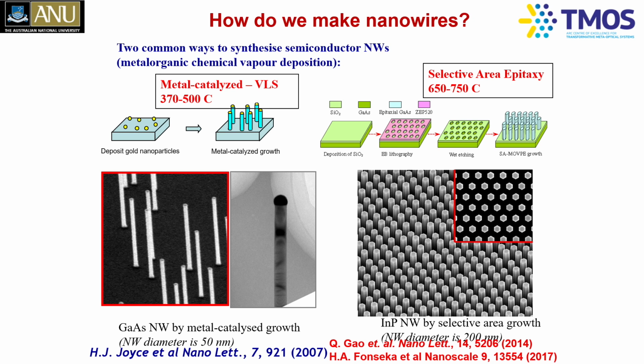Put this into the MOCVD reactor, heat up to somewhere between 650 to 750 degrees Celsius, and introduce the gases needed for the growth of indium phosphide, so trimethyl indium and phosphine. These gases dissociate, and then nanowires will start growing in these holes. This is the work of my former student, Dr. Qian Gao. She's now a research engineer at BluGlass in Sydney. You can see that she can make beautiful indium phosphide nanowires, in ordered patterns, because we created ordered patterns of these holes.